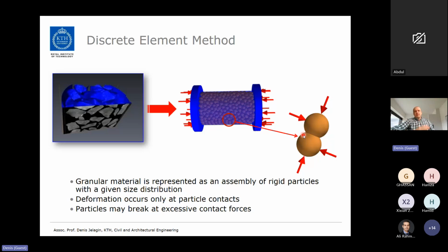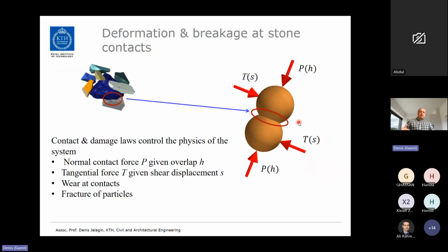And this amount of penetration will be somehow dependent on the amount of force we apply to a given contact. They can also, if they are loaded tangentially, slide with respect to each other. And if contact forces become excessive, particles can break. This particle breakage can also be modeled in different ways. So basically, those contact and particle damage laws are the two main parameters which completely define the physics of the system, and they are extremely important. Basically, what we are after is developing accurate contact and damage laws of the particles.